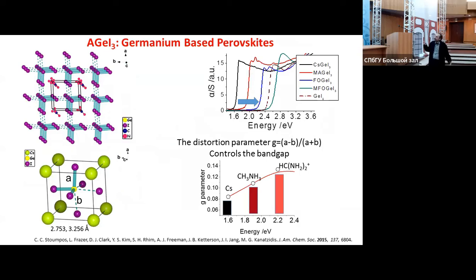And I would like to say that these types of materials happen mostly with lead as the bivalent metal, or tin. But there is another metal that we can use from the periodic table, and this is germanium. Germanium perovskites are a little bit special. They have the topology of the perovskite, so the metal and the halogen connect in the same way, but there is a difference in the sense that germanium is not in the center of the octahedron. It's shifted towards one direction along the body diagonal, and this forms a situation where you have a small bonding distance and a larger non-bonding distance.